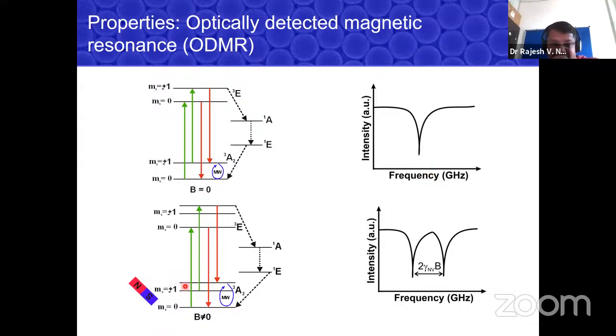And if you apply a magnetic field, you can use Zeeman splitting to split the levels. And instead of one dip, you get two dips, because there's a transition to two levels, which are now split by the magnetic field. And this is the essence of magnetometry using NV center. And you can have a commercial NV center magnetometer you can buy for your lab, and you keep a sample, you can map the magnetic field, and do magnetic imaging. And this is where people talk about quantum sensing. Okay, basically what they mean is very ultra low field sensing using NV center, because this defect state responds to the magnetic field, and you can read it out using optical techniques.